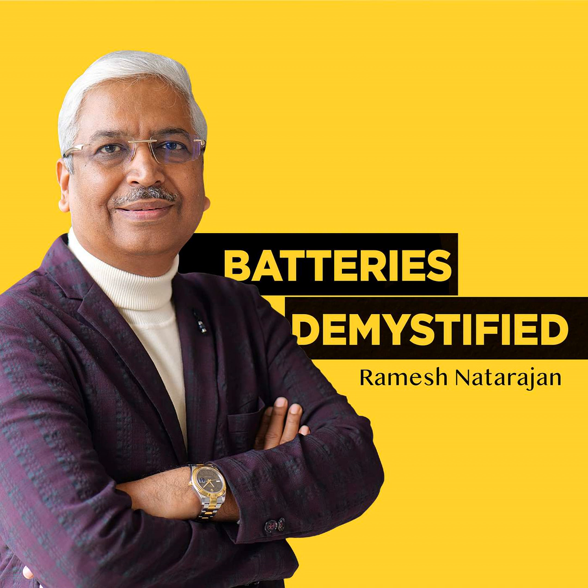I could imagine that more Vanisperse HT1 or DCA would then be pulled out of the negative at high temperature, but I would think that they'd be more likely to remain dissolved in the electrolyte. Whereas with Vanisperse A, I don't think high temperature would pull more of it out of the battery or more out of the electrode. And if it did, I would expect it then to precipitate more quickly as that temperature stayed elevated and if that acid were more concentrated. So at high temperatures, it's just very hard to say.